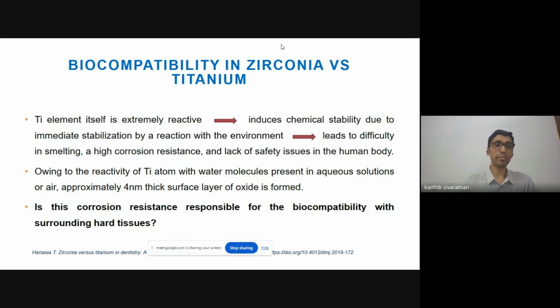Now, the titanium element itself is extremely reactive, and it forms a surface layer of titanium dioxide. Even if this titanium dioxide is scratched and removed, it tends to repair itself, which gives an impression that it's very passive in nature. And this is the reason why it is supposed to have a high corrosion resistance, and there is an apparent lack of safety issues in the human body. But the important question here is: is good corrosion resistance responsible for the biocompatibility with surrounding hard tissues, or are there additional factors?